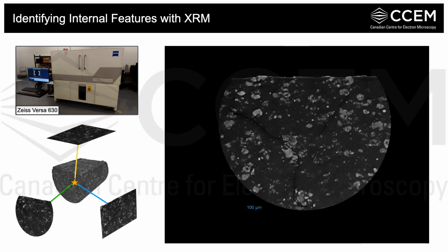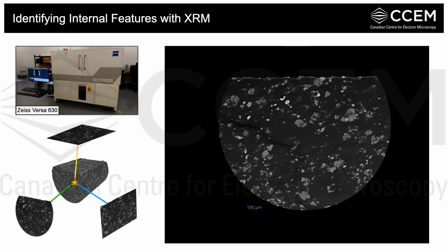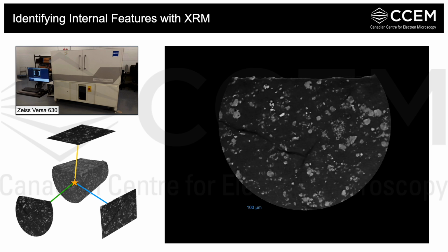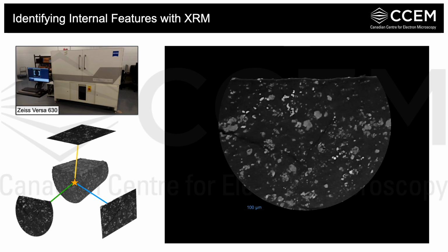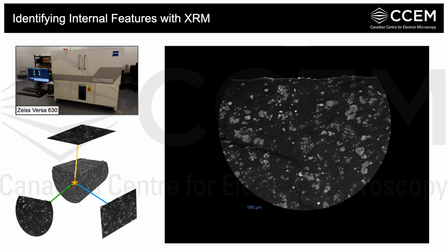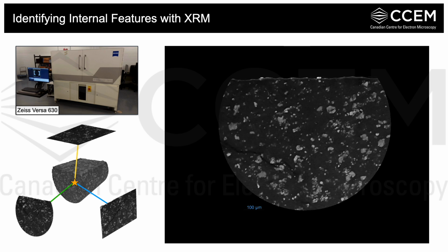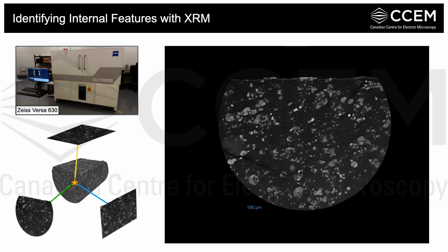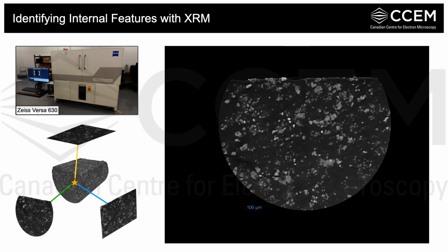So this video is showing a slice-by-slice progression through the volume, and we can now better see the distribution and sizes of the clasts. We can also see other internal features like annealed and open fractures. We can see how they propagate through the data, and we can see the distribution of clasts relative to these fractures. So overall, this is providing us with kind of out-of-plane context, which we wouldn't get with our traditional SEM or FIB cross-sectional image.